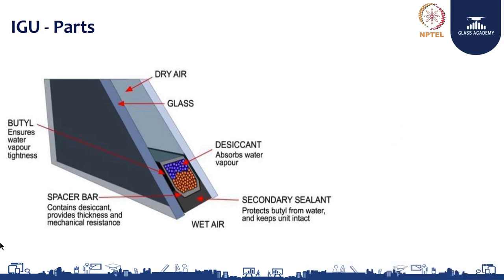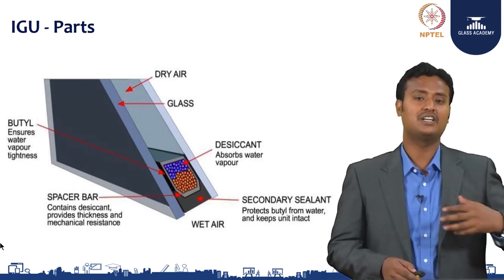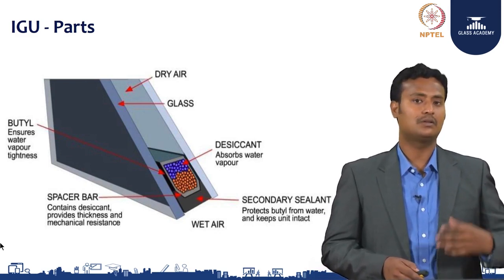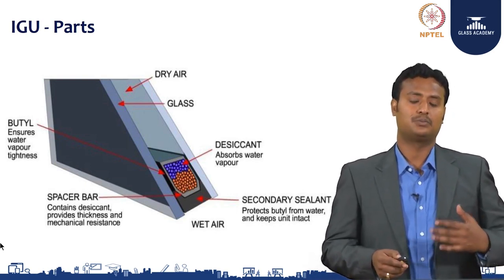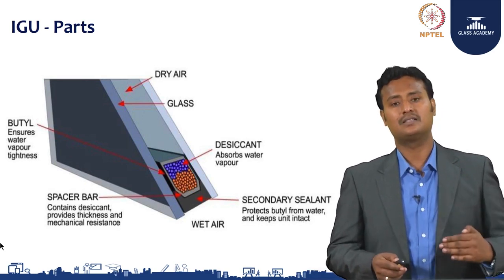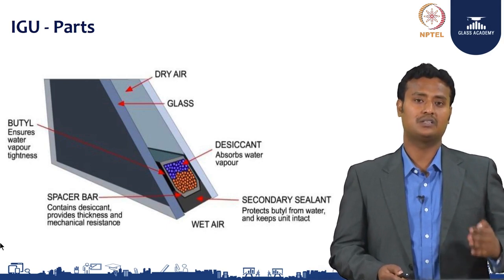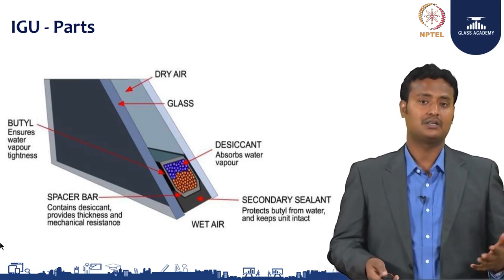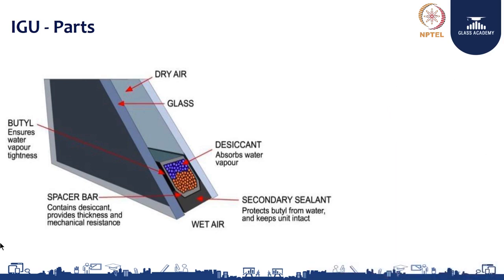The butyl enables the glass to move from its original position by 2 to 3 mm. Next is the secondary silicone, which protects from exterior conditions like water vapor, chemical vapor, rain, and sun exposure. The secondary sealant gives structural strength to the IGU as well as preventing abnormal conditions like water, humidity, hot gases, fumes, or chemical agents from penetrating inside the DGU.